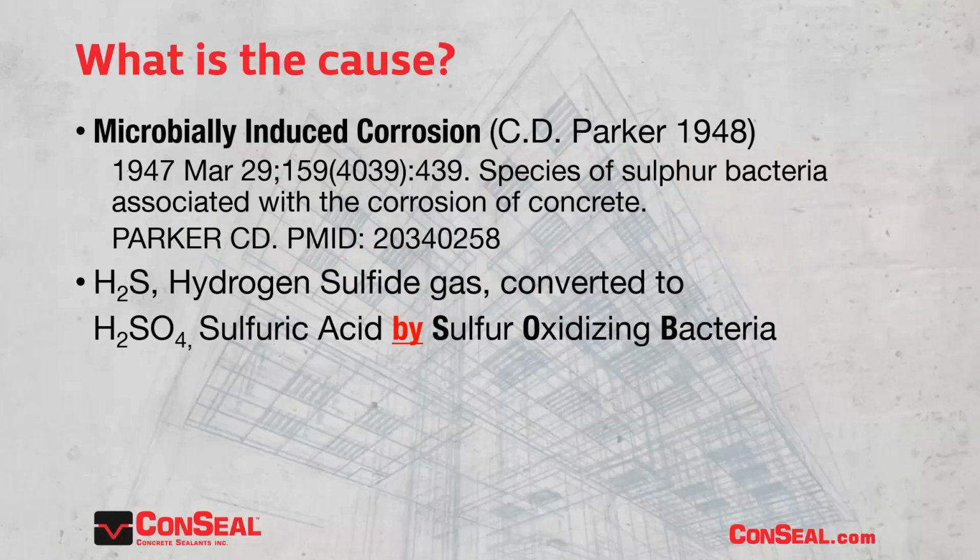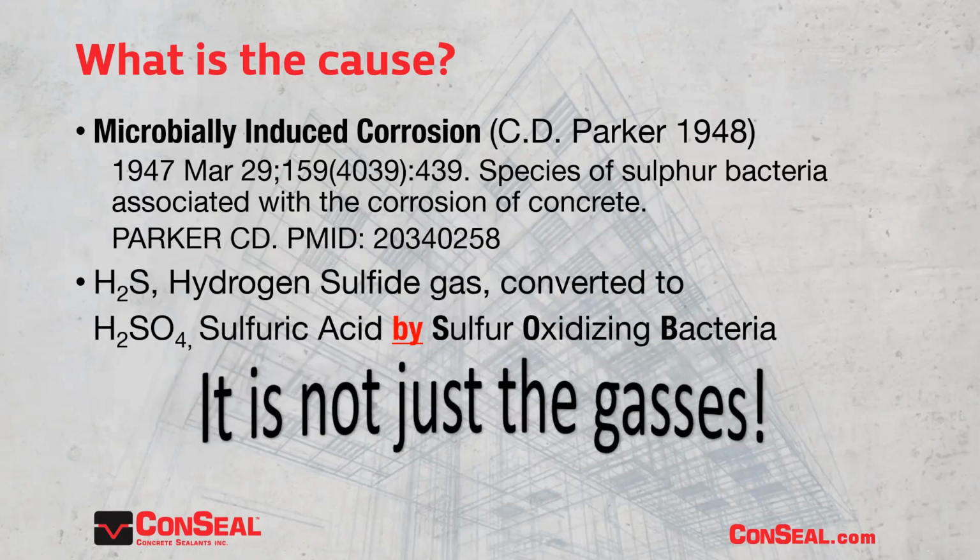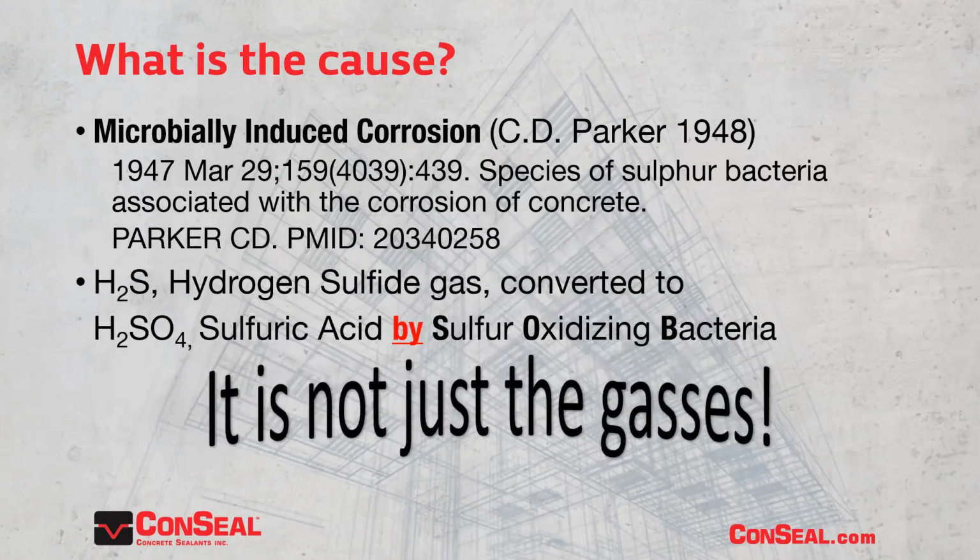What's important to understand here is that microbial-induced corrosion is not a new phenomenon. It was C.D. Parker back in 1948 who actually discovered that it was bacteria that was causing the corrosion. The bacteria consumes hydrogen sulfide gas that's present in sewer systems, and it converts that hydrogen sulfide gas into sulfuric acid, and this is done by a sulfur oxidizing bacteria. So it's important to note that it's not the gases that are causing the corrosion, it is the conversion of